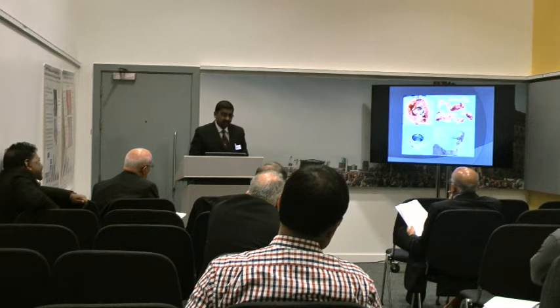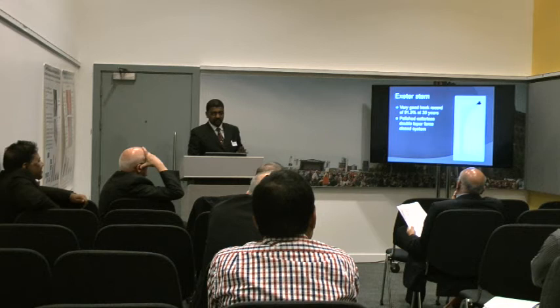Now, the stem we are using is a standard Exeter stem. It has a very good track record, 91.5% at 30 years. Polished, collarless, so I'm not going to bore you with that. The taper is a patented V40 taper. The V40, it's not a V, it's actually a Roman numeral 5. I actually asked Stryker what the V stands for. It's a 5 degree inclination of the taper. Unlike a 12-14 taper, this is a 5 degree inclination of that taper, so it does make a difference.